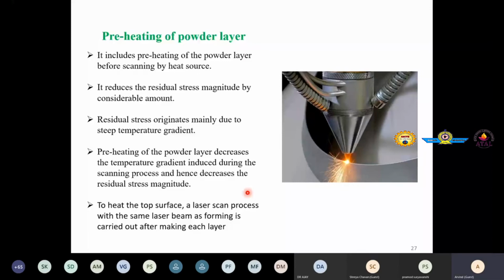In electron beam based powder bed fusion process, this preheating is very common, because the advantage of the electron beam is that it can scan a layer very fast because it is based on magnetic coils, not on optics and galvanometer. So there the production time will not be compromised, and in electron beam processes, this preheating of the powder layer is very common, and that is one of the big advantages offered by electron beam.